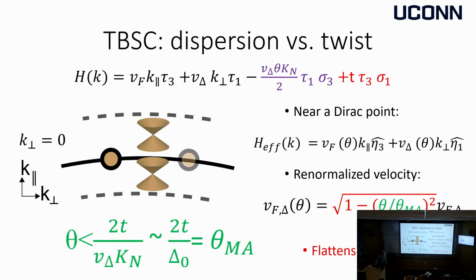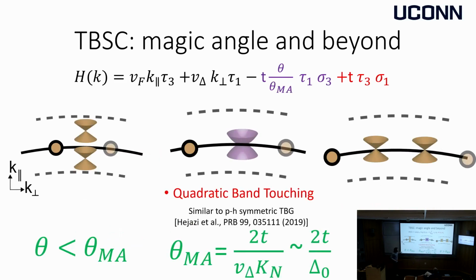Okay, so what happens at the magic angle? In this model, you just know the answer. And the answer is that these 2 points collide, forming a quadratic band touching. And as you go to a twist angle larger than the magic angle, this quadratic band touching again separates into 2 Dirac cones going in opposite directions. So there's just one magic angle.